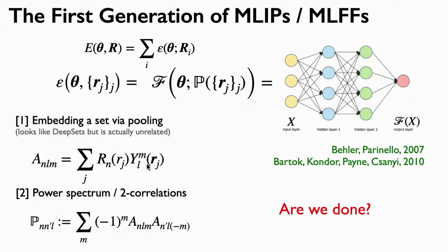So you know, these are the vector distances to the neighbors, these are the radial distances. Through a pooling operation, you generate a permutation invariant descriptor of the atomic environment, and then you take symmetry adapted correlations of this in order to make sure that this descriptor vector becomes really invariant under rotations.